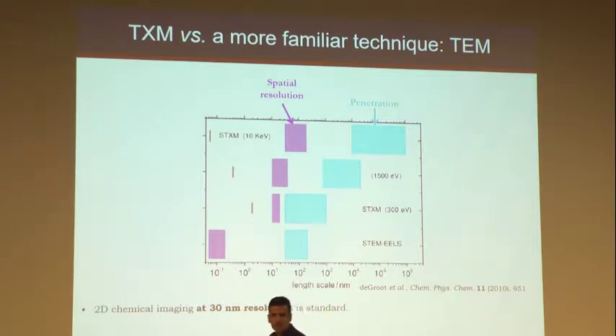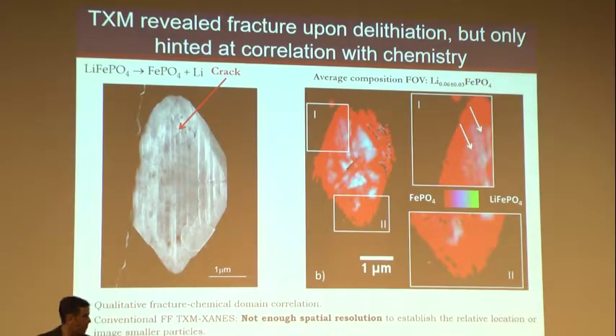This is the spatial resolution graph. This is a graph from 2011, I believe, 2010, where it compares, of course, with TEM. But it allows me to set the stage for the fact that when we started this work, the spatial resolution was typically around 30 nanometers with chemistry. Okay. And with this is where we did these measurements. This is a particle of lithium iron phosphate, one of the battery materials in that map that I showed you before. You can remove lithium and you get iron 2 going to iron 3. And so what happens is that if you stop halfway, you have a mixture of the 2. And then you can map where they are in your particle.